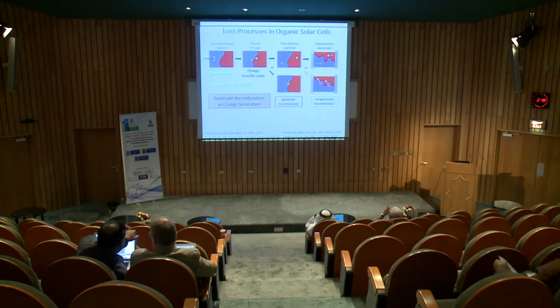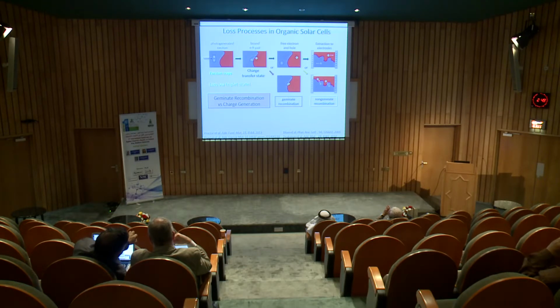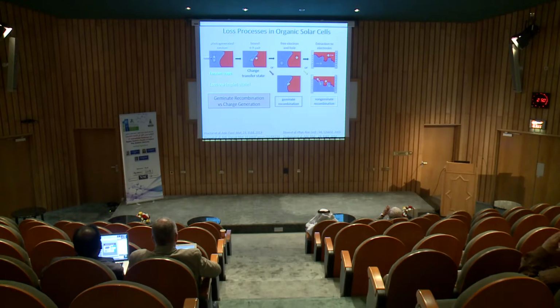And so before I go on, I want to highlight that there are different loss processes that happen in organic solar cells, and also in silicon solar cells, dye-sensitized solar cells, or perovskite solar cells. So you have similar types of losses. When your material absorbs a photon and creates an excited state, which we call an exciton, the exciton can also encounter a trap. And if they get trapped, they're not going to go to the donor-acceptor interface where they can do electron transfer. For those that make it to the donor-acceptor interface and do ultrafast electron transfer, if the electron and hole are still strongly bound across the interface, which scientists call the charge transfer state, there is a higher probability for them to recombine and go back to the ground state.